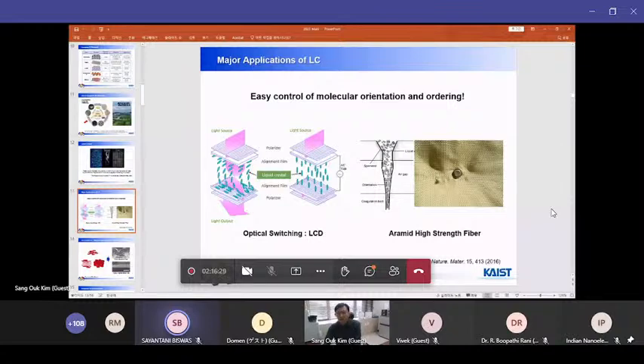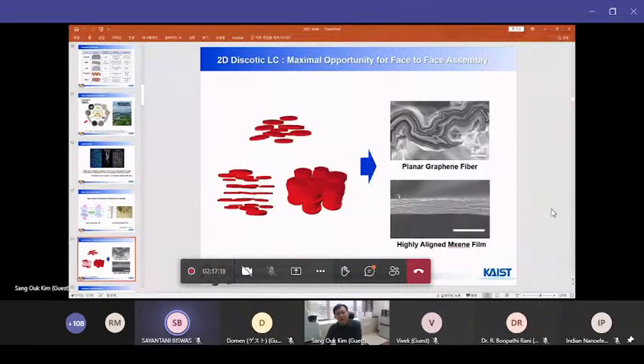The right side shows extremely strong liquid crystalline fiber formation, like aramid fiber. In this case, you usually use a high molecular weight polymer liquid crystal. Usual polymers can also be fiber spun, but the molecular orientation is rather low because of the intrinsic entropic elastic behavior of a single polymer molecule. But in the liquid crystalline state, you can get highly ordered molecular orientation in the final polymer fiber. This easy controllability of molecular ordering is a general feature of liquid crystalline materials.